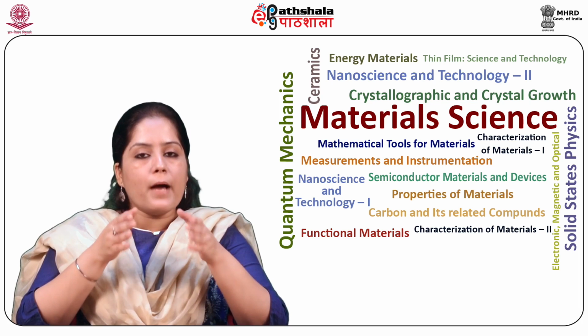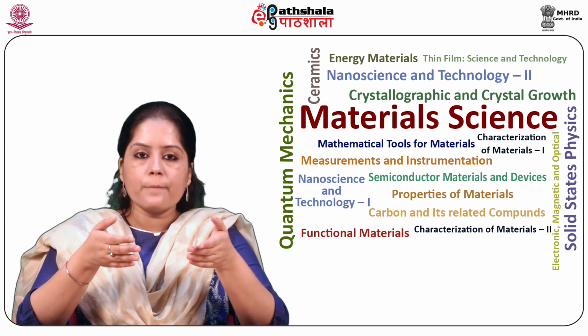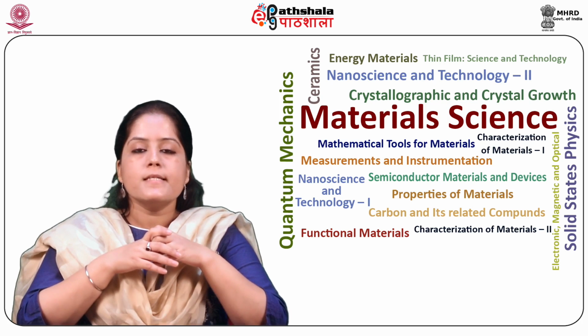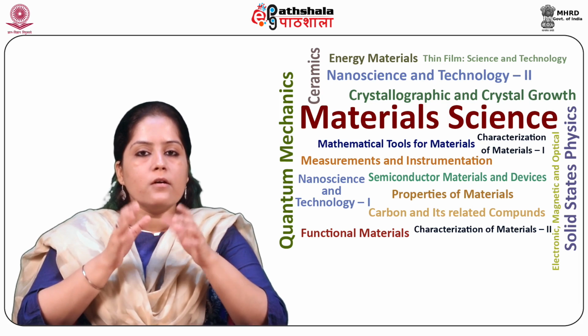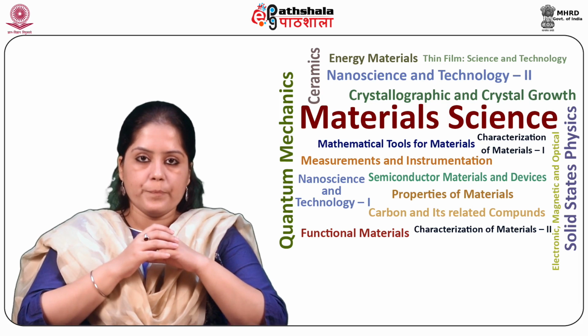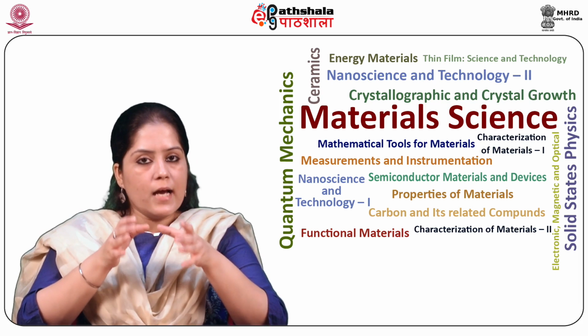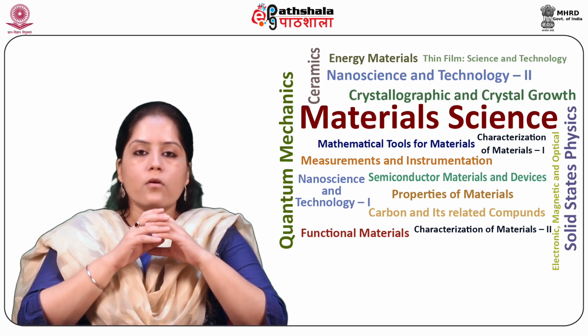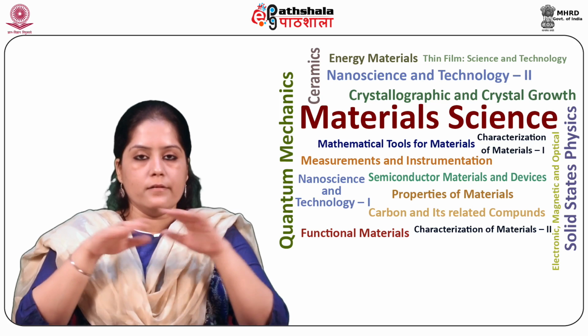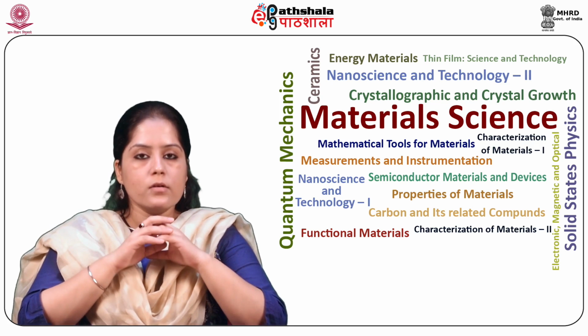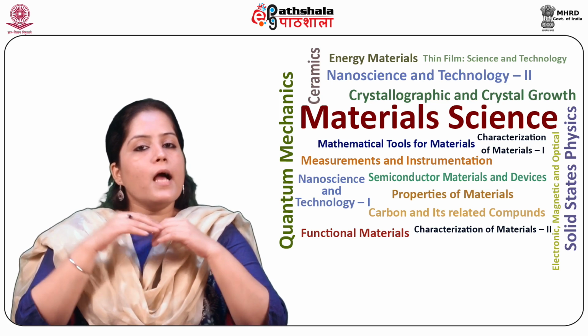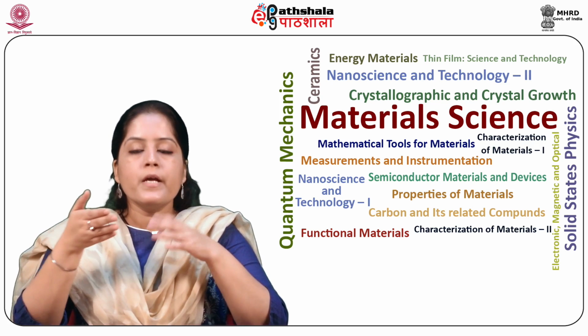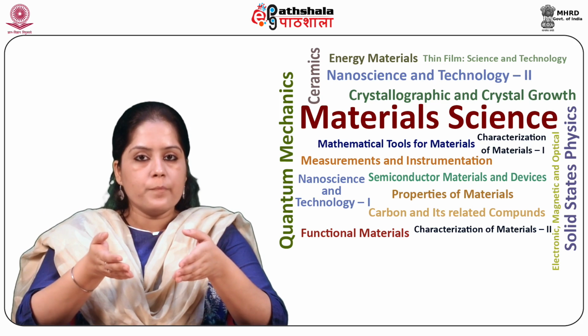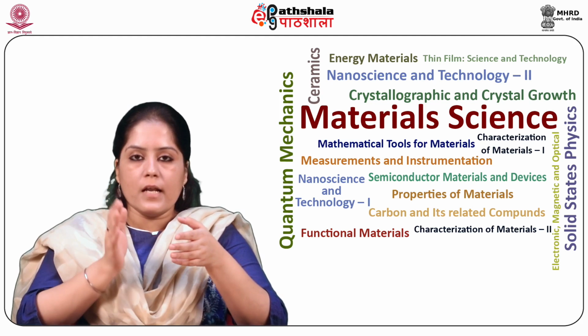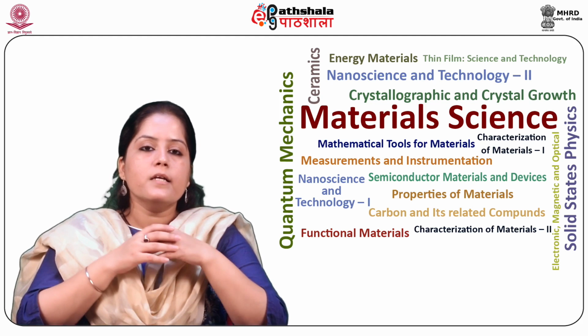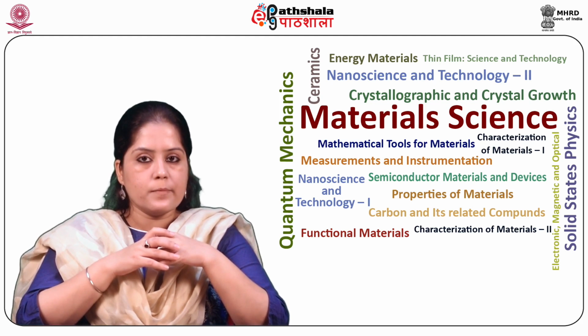It acts as a barrier for impurities and dopants, safeguarding the purity of the silicon wafer. This highlights the role of silicon oxide as a masking layer. Silicon oxide is stable at higher temperatures, has a wide band gap, very high dielectric strength, and insulation abilities.